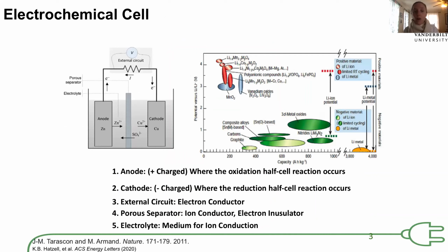So you all are electrochemists, so I can kind of skip through this. But typically, we use intercalation cathodes as the cathode for a lithium ion battery, and we'll use a graphite or alloy type composite, graphite and silicon, as the anode. But there's a significant interest in using lithium metal because it has a lower thermodynamic potential. So we can eke out slightly higher voltage windows when paired with lithium cathodes.